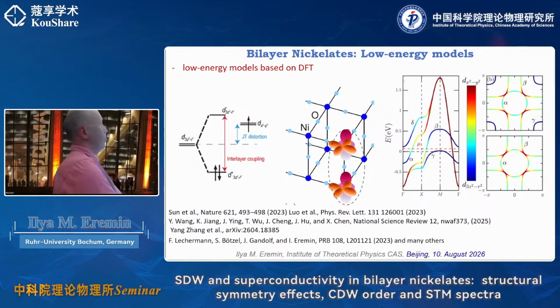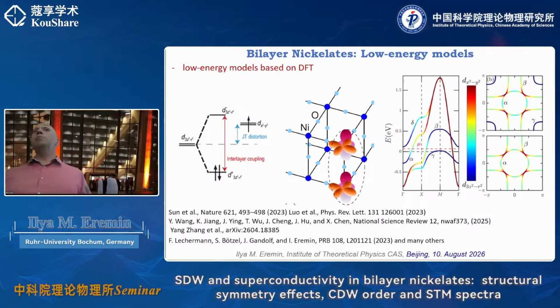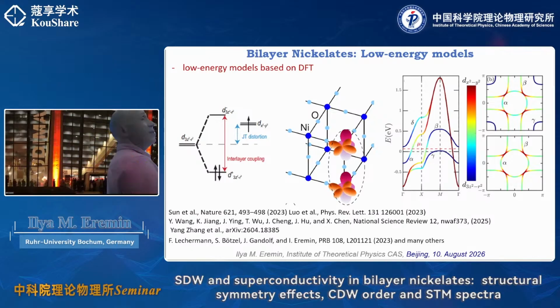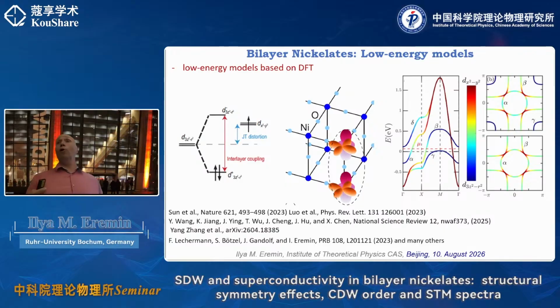So if you look at the Fermi surface, this is the Fermiology that you have. Sometimes people were wondering whether this gamma pocket is crossing the Fermi level. So it's known that in a bulk crystal, it doesn't, at ambient pressure, and I will be talking about this as well. Then you are dealing with this topology, Fermiology. And it's actually quite interesting because in principle, you can have a legitimization of different types of model. You can consider dz² to be completely occupied, being essentially localized-like. Of course, it's not what comes out from the DFT, but that's what one part of the theory assumes. You're effectively dealing with the dx²-y², which is strongly split.